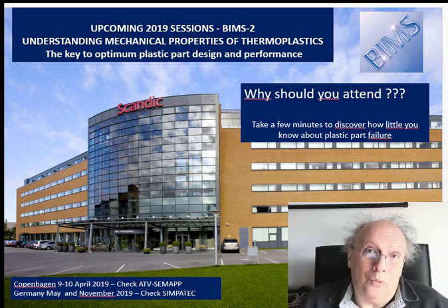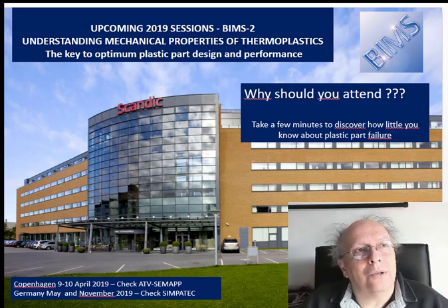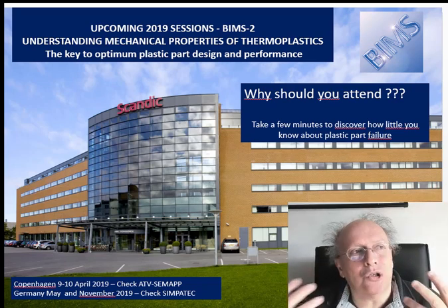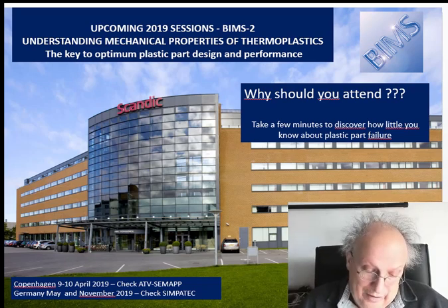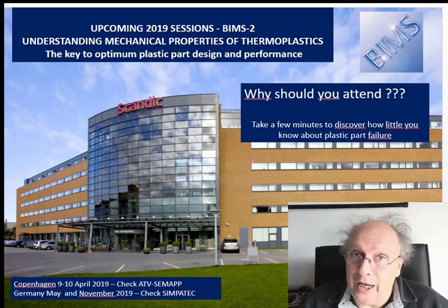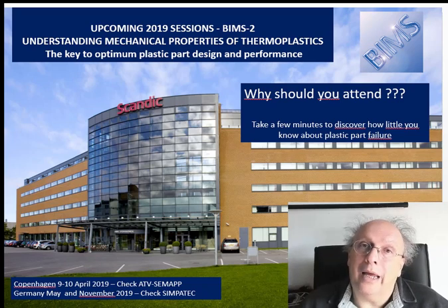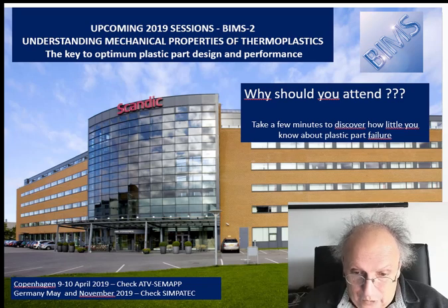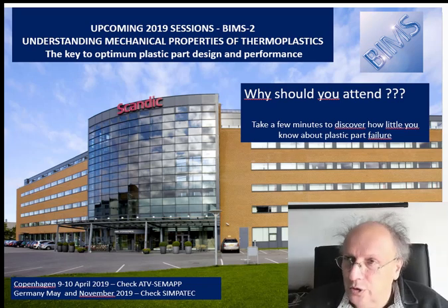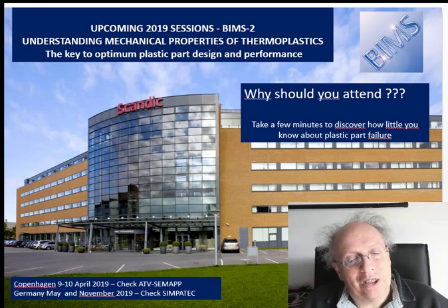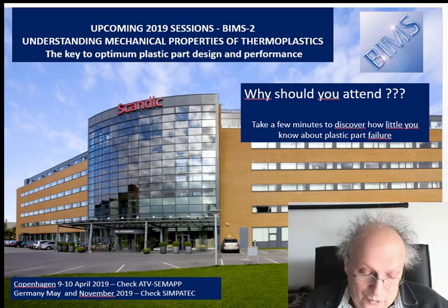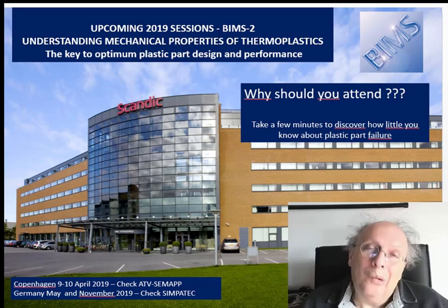So this is all about what we call triaxiality, the sort of 3-dimensional level of tension. And it turns out that that's how polymers fail in a brittle mode. That's when the global 3-dimensional tension is so high that you start cavitating and creating a crack. Okay, so we'll look at that in detail, and I'm sure even the most seasoned of you professionals working in plastic part design will find it interesting, and learn something.